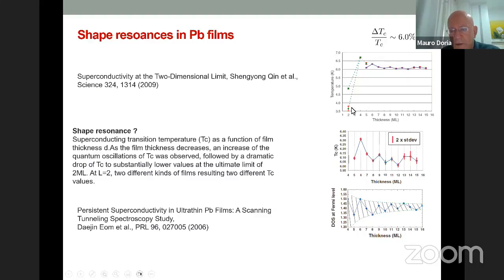And you see that for 2 monolayers, you have nothing. But then if you go from 4 to 15, you begin to observe an oscillation in TC, which is just enhanced. Here is a small effect. Temperature goes from 635 to 610. It's a small oscillation, okay?